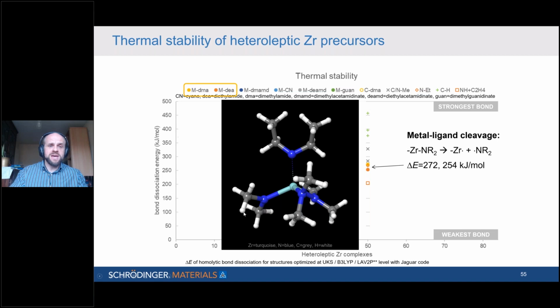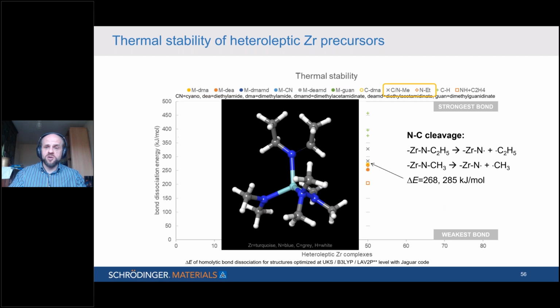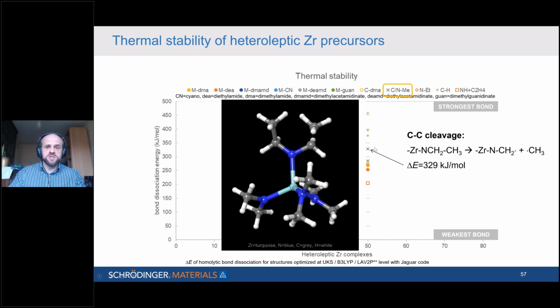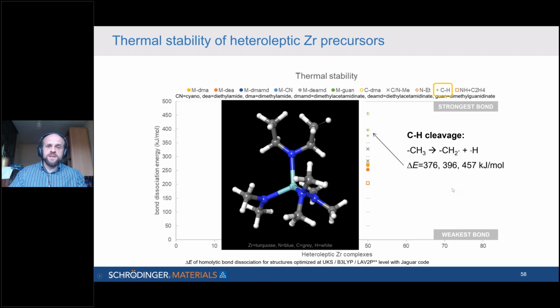So first we're going to look at the metal to amide dissociation, which is depicted here. And if we break that bond apart and compute the energy that it requires to generate the 2 radicals, this costs 272 or 254 kilojoules per mole. So that's plotted on the graph as the yellow and orange circles. And next we can look at the nitrogen to carbon bond cleavage. Again, there's a couple of possibilities for that, and they're shown as crosses and diamonds. We can look at the carbon-carbon cleavage, which is shown as this particular cross at 329 kilojoules per mole. Then there's the carbon-hydrogen cleavage, much higher in energy, 370, 390, 450 kilojoules per mole. Those are shown as green pluses.